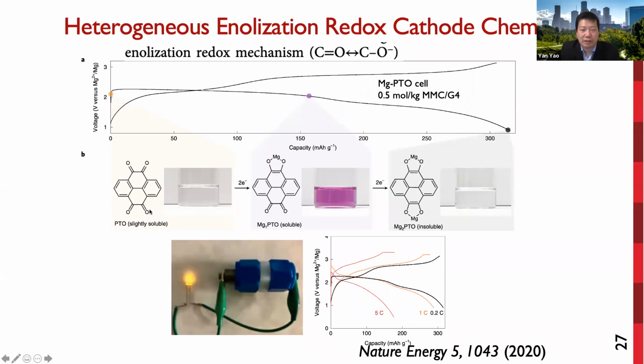PTO was again selected as a model compound due to its high theoretical capacity and solvent-free magnesium storage. The voltage profile consists of two plateaus, each corresponding to a 2 electron reaction. The average discharge voltage is about 2 volts, and the capacity is about 315 milliamp hours per gram. Both of these values represent some of the highest values for magnesium batteries.